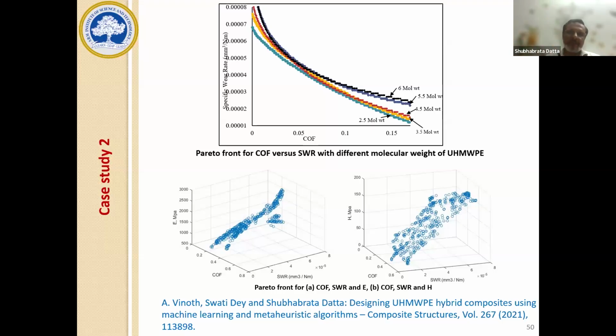That was the fourth type of particulates, and we made all the possible combinations and characterized it, and we found in some cases it was giving excellent specific wear rate. It is expected that the strength will increase, providing harder particulates like CNT, graphene, or carbon fibers. So it is expected the strength will increase, modulus will increase. That was expected. But the thing which we were happy to achieve is that the specific wear rate, in some cases, was really low. So this was the second case study.